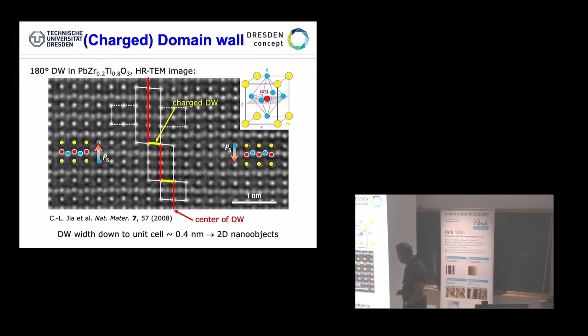What we expect is that, if we look on an atomistic scale, this domain wall, which is inclined by a macroscopic angle, let's say 0.1 degree, should be made up of reddish areas, that means ordinary 180 degree domain walls, which are non-charged, and then charged domain wall plateaus, shown here in yellow, where we make one step or two steps depending on how large our inclination is.